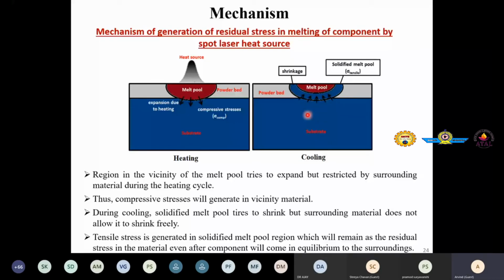So you see very easily that a region in the vicinity of the melt pool tries to expand but is restricted by surrounding material during the heating cycle. Thus, compressive stresses will generate in the vicinity material. However, during cooling, the solidified melt pool tries to shrink, but surrounding material does not allow it to shrink freely. As a result, tensile stress is generated in the solidified melt pool region, which will remain as the residual stress when it cools down to ambient temperature. So this is one location, right?